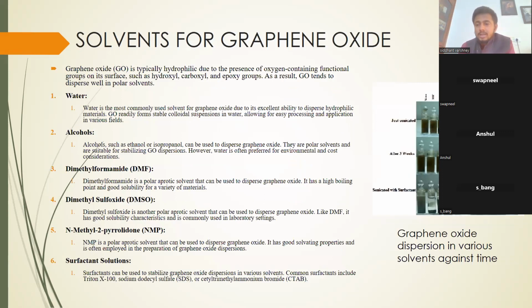Then solvents for graphene oxide, as I told you, there are many solvents. You can play around with the Hansen solubility parameter, HSP. HSP decides the polarity, or whether a substance goes well into a polar solvent or a non-polar solvent. But this goes into both polar and non-polar, although the solvent has to be slightly polar, which many solvents are. Not many solvents are completely non-polar. So graphene is suitable to a large plethora of solvents: water, alcohols, dimethyl formamide, DMF, DMSO, dimethyl sulfoxide, N-methyl-2-pyrrolidone, NMP, even surfactant solutions for exfoliation, and all kinds of surfactants.